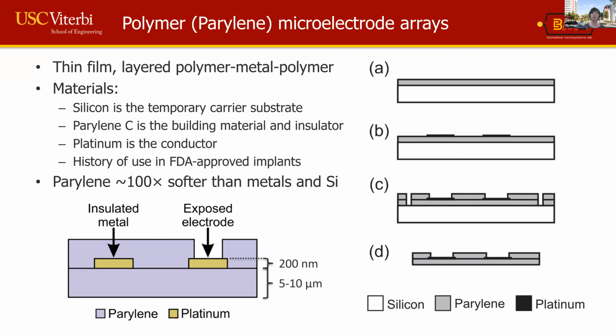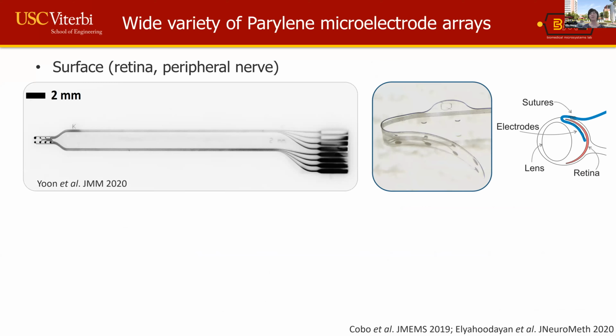The construction, here's a cutaway view, a cross-sectional view of what a typical device might look like along an electrode site as well as along a trace. We use typically 5 to 10 microns of parylene per layer, and the electrodes are about 200 nanometers. So that gives you an idea of scale, and the width and the specific geometry will vary based on the application. And I'll kind of show you what we can do with these devices.